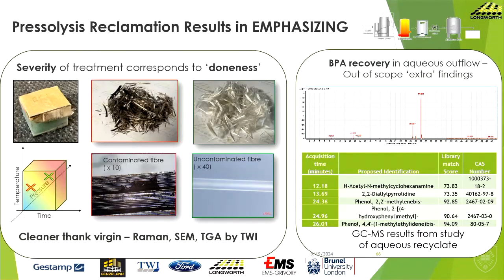So we're just looking on the left-hand side now. Through about a year's worth of work, we've come up with a severity of treatment where we can convolute the temperature, pressure, and time variables to quantify the severity of how hard you hit that material. As you can see, these wind blades were full of wood. They were epoxy-based resins. If you hit at too low severity, you're going to get some depolymerization, you're going to get some char formation. But if you push that further up, you can find a spot. So there's a lot of room for optimization.